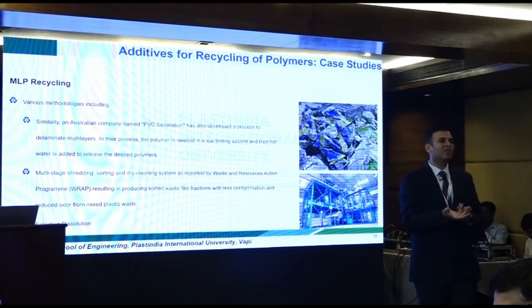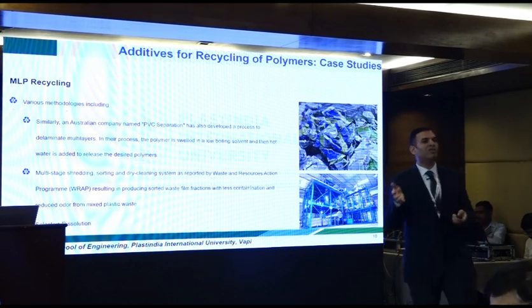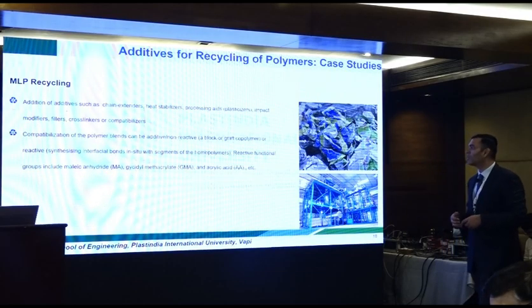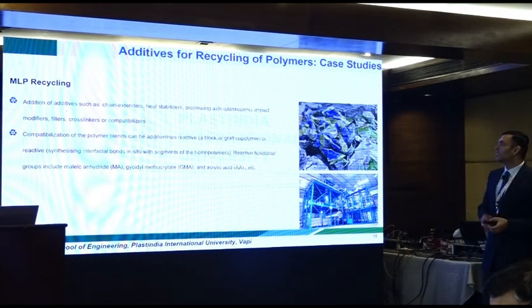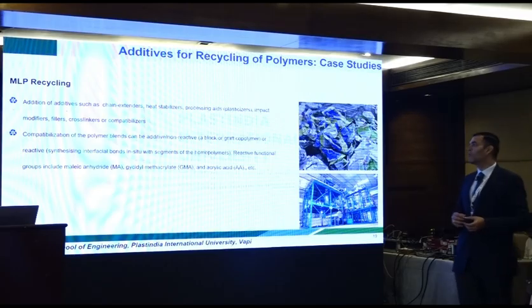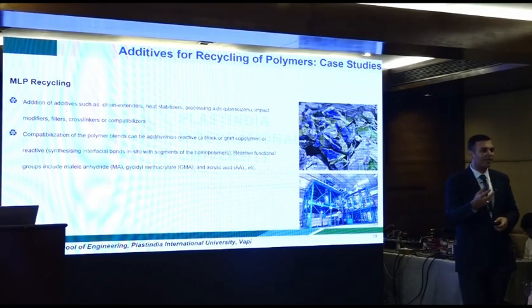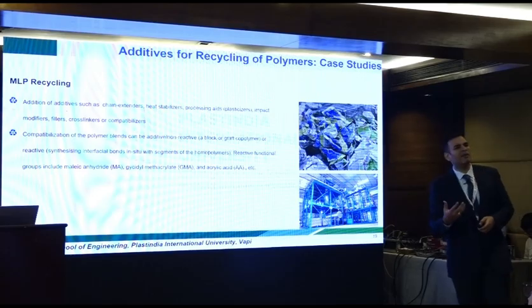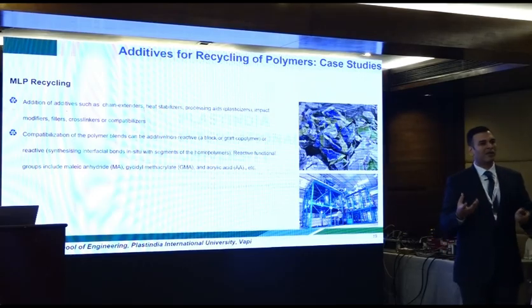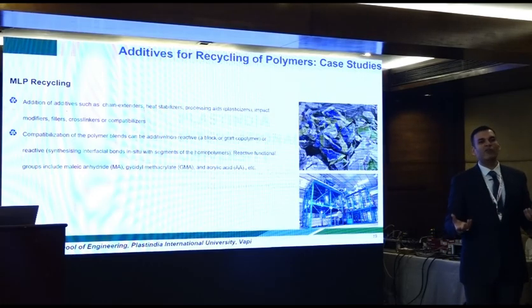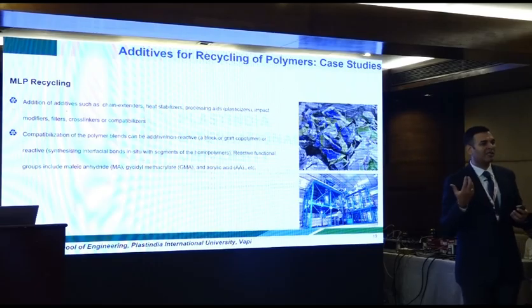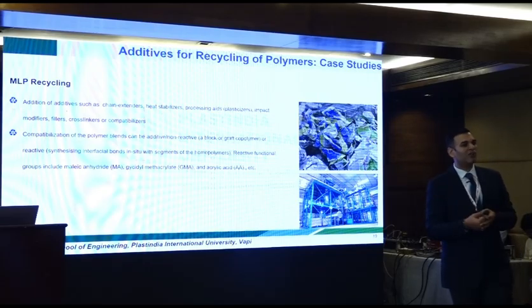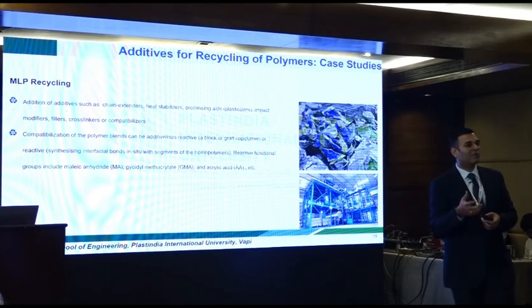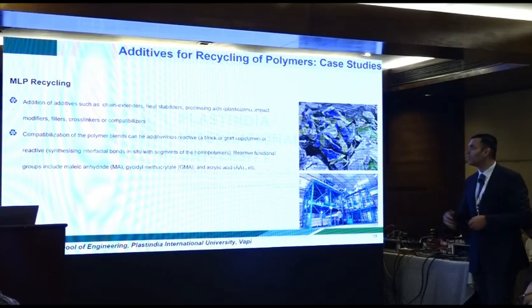But then it is a costly process. You do the same for the second, you do the same, and the third one is separated out on its own. Addition of additives such as chain-extenders, heat stabilizers, processing aids, impact modifiers, filler, cross-linkers or compatibilizers. So a host of additives that you can add. There are companies who have come up even in India who started consuming MLP, trying to create innovative products using this multi-layer packaging, and they are able to sort of bind these metallic layers, which is the problem earlier. So that is where these cross-linker and compatibilizers come into the picture.